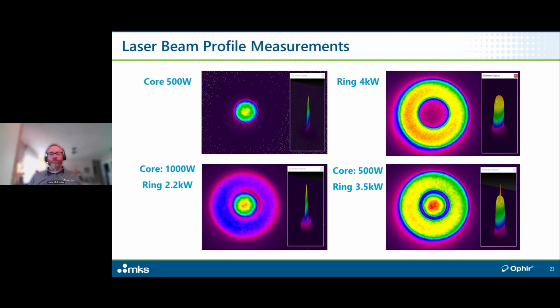Here are some additional images that I took on this ring core laser at the KUKA lab. The top left is the core at 500 watts. The top right is the ring at 4 kilowatts, and you see that the intensity between those two at the top is roughly the same. You're getting into the yellow, so it indicates about the same power density. But you notice, obviously, the ring is of a larger size. So since you are at 4 kilowatts, where the core is at only 500 watts, about an eighth of the power level, you get the same power density between these two beam shapes.